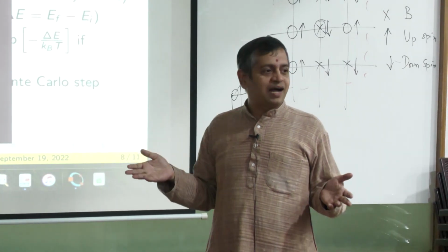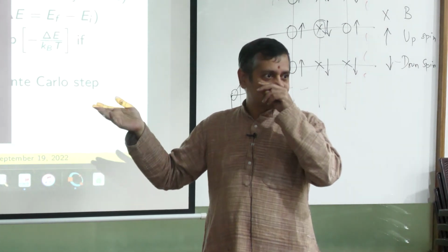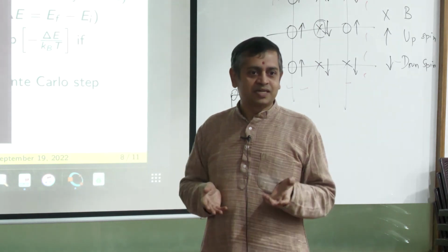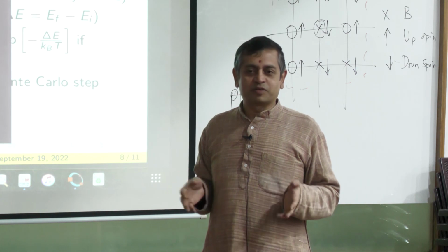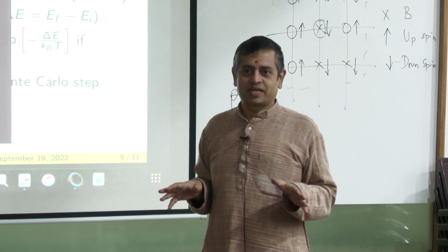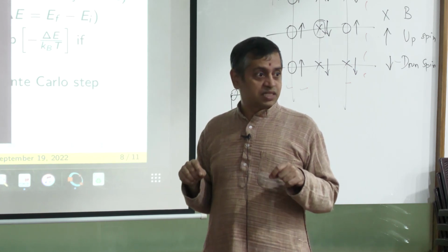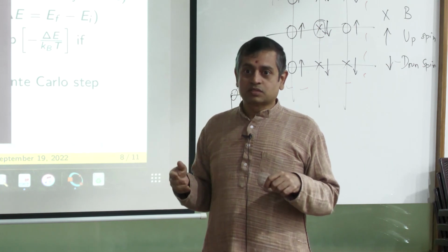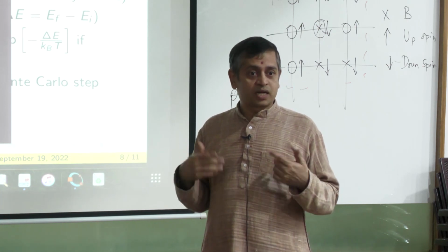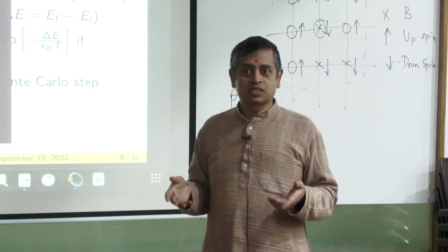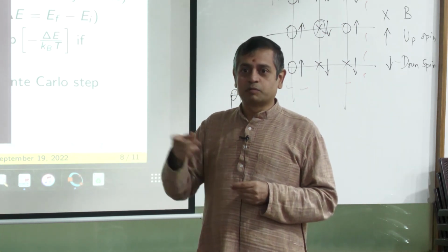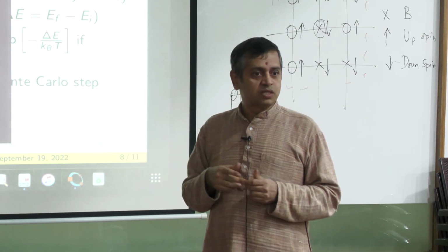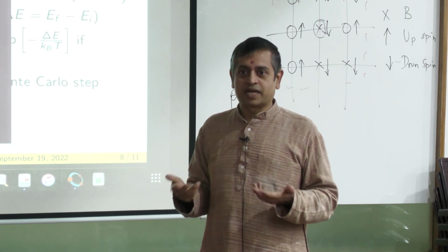Sometimes you do not even have that many atoms in the simulation cell, maybe you are doing 300, maybe the vacancy concentration is 1 in 10 power 8, and you do not have 10 power 8 atoms in your simulation. So, introducing a vacancy will lead to artificially quicker simulations, because it is equivalent to having a much larger number of vacancies, like in the aluminum copper that Freddy was referring to. The quenched-in vacancies make the dynamics faster.